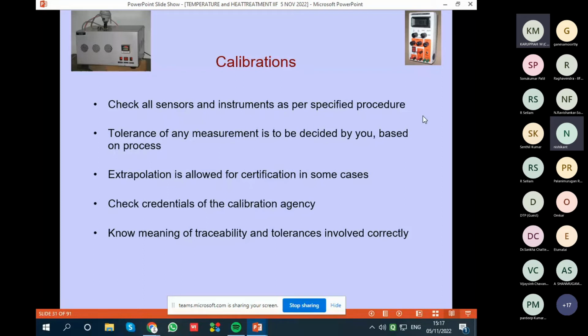So what we do, we put the thermocouple in the furnace on the left-hand side. And there is a master thermocouple, which is also put there. There is a small instrument. We set the temperature at which we want to test it. Let us say we want to test it at 200, 300, 400, 500. So we set it there. Then the furnace automatically goes to that temperature and stabilizes. You can see on the right-hand side, there is a calibrator. So we measure the temperature on the calibrator along with the master and compare them and find out whether there is any variation, whether it is within the tolerance and all that.